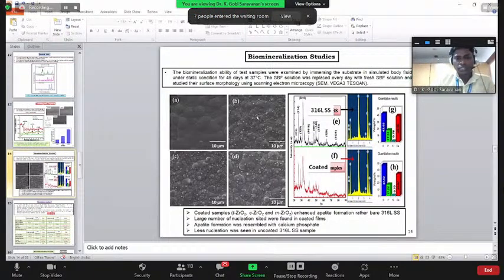Then after that we also took the XRD. What are all the minerals present in the coated material? It shows calcium phosphate on the coated sample. This is a mineralized sample. That indicates that apatite formation has happened on the coated implants.